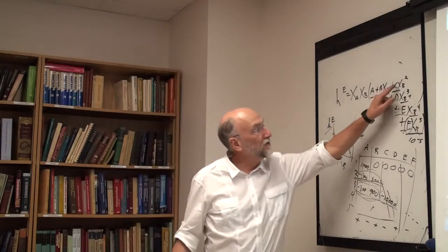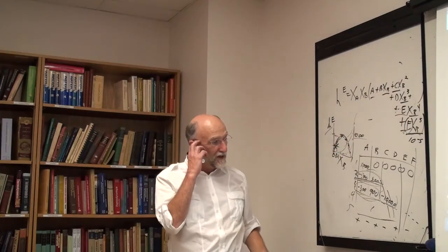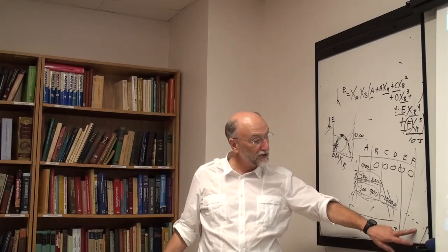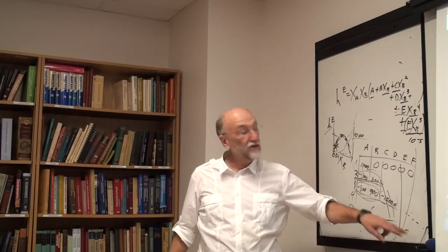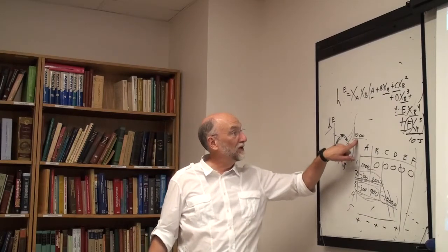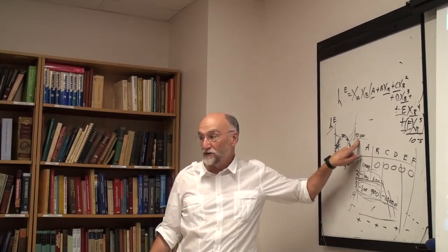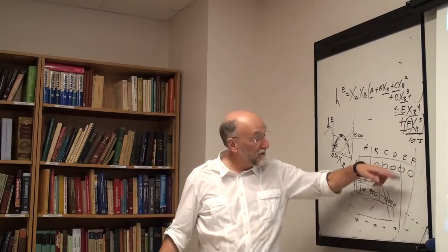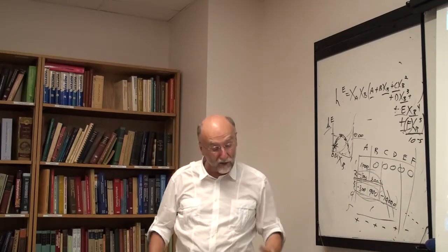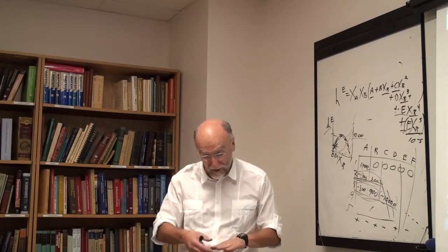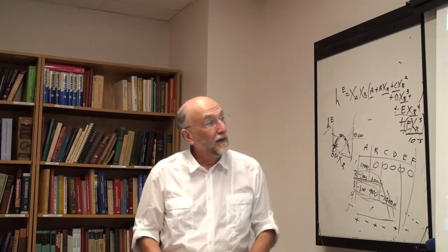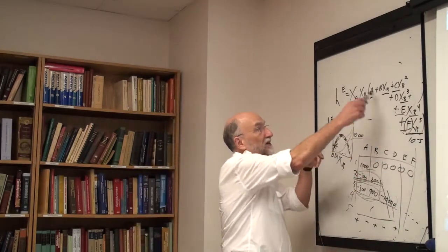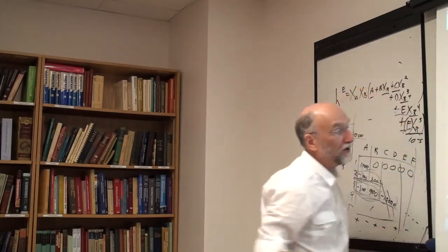Even just curve fitting with the computer, you very quickly get into double precision calculations. You can't keep 8 significant digits, you've got to do 16. You say, well, I'm only trying to fit 1,000 joules, it's only accurate to 10 joules, I only need 3-figure accuracy. No, you don't. You could need 16 or 20-figure accuracy if you go to enough terms. So you have to do everything in high precision, and you get round-off errors, and so there's your problem. Even once you rearrange all these terms, you would end up with a polynomial that looks like that.